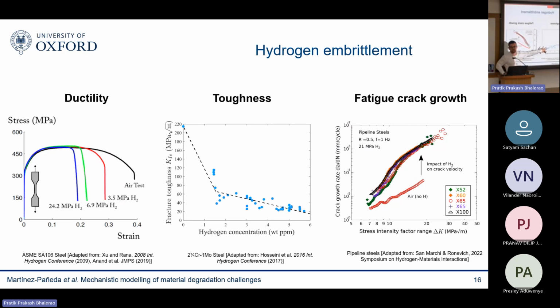And this is a pressure vessel steel, so very relevant to hydrogen storage. And these are pipeline steels. This is fatigue crack growth rate, so crack velocity in a log-log plot. And you can see that in the absence of hydrogen, you are here. But the moment you bring hydrogen into the picture, you increase by at least an order of magnitude the crack velocities in hydrogen-containing environments. So that's, of course, a challenge. You have very ductile metals behaving almost as brittle as ceramics, and you need to store and transport hydrogen.